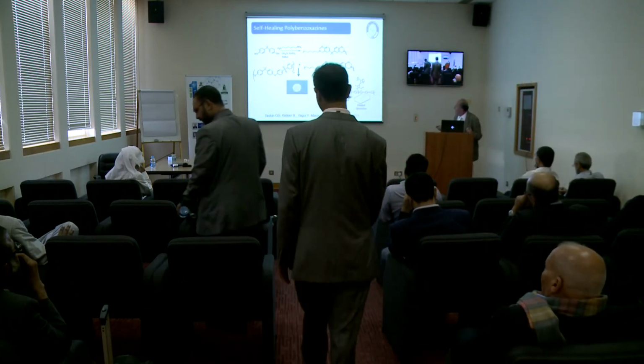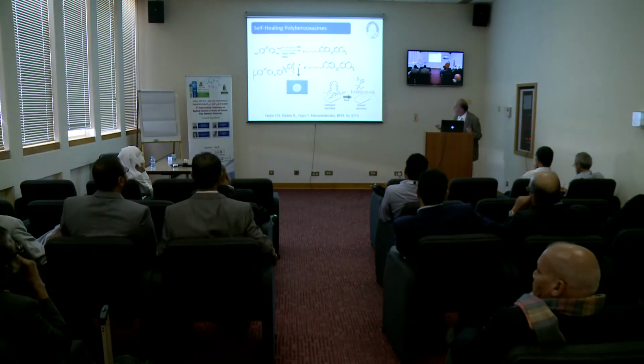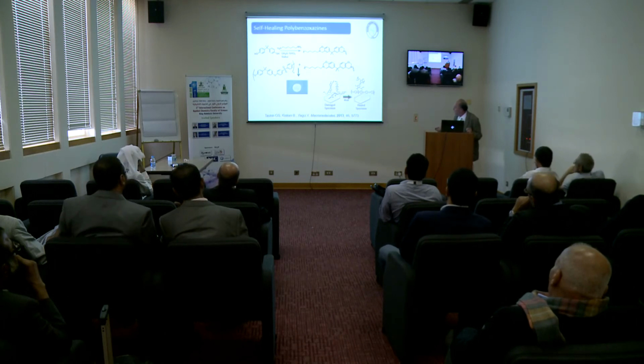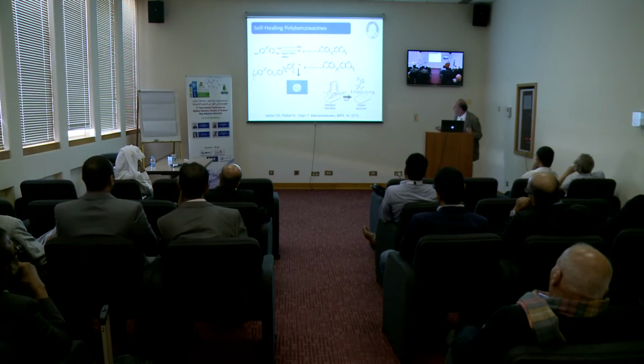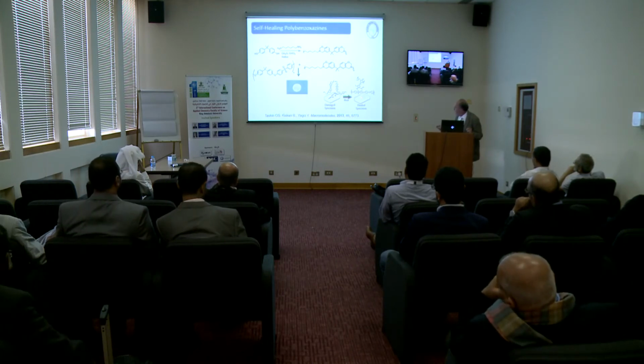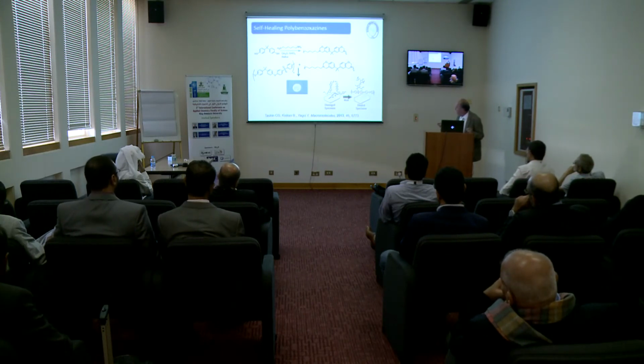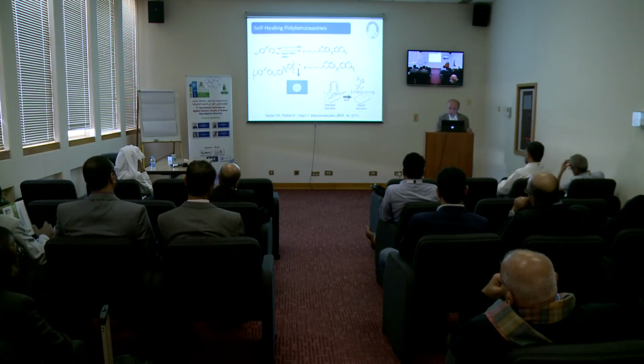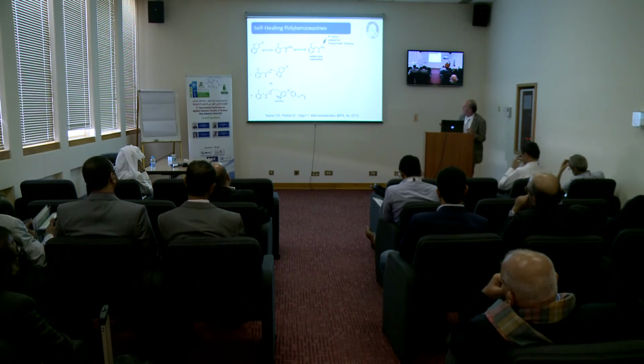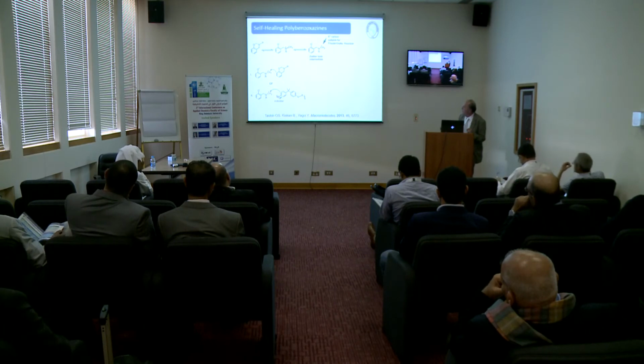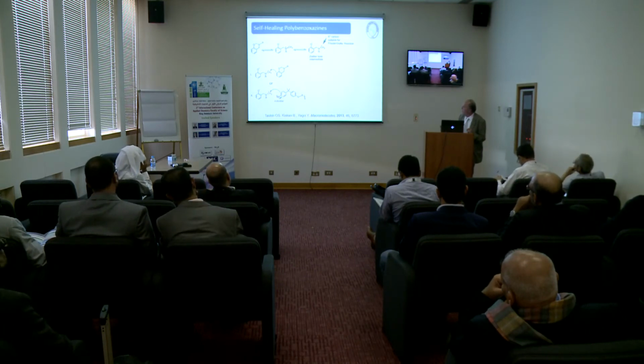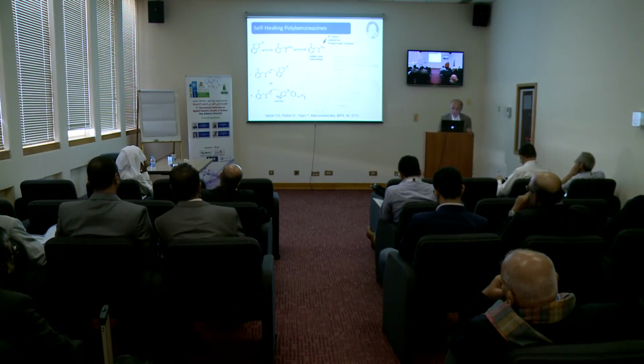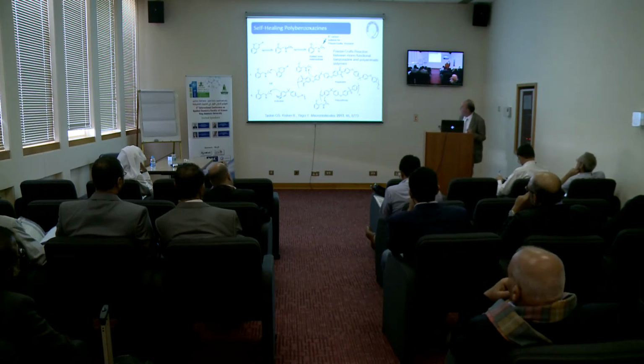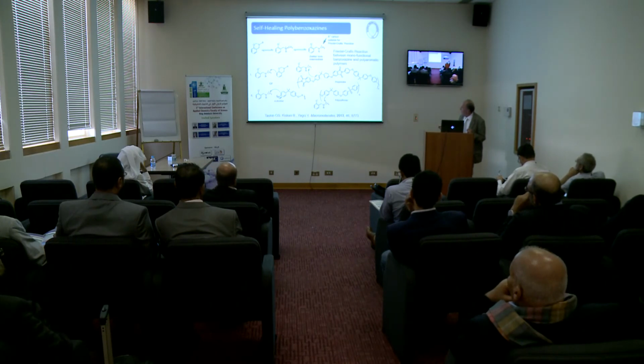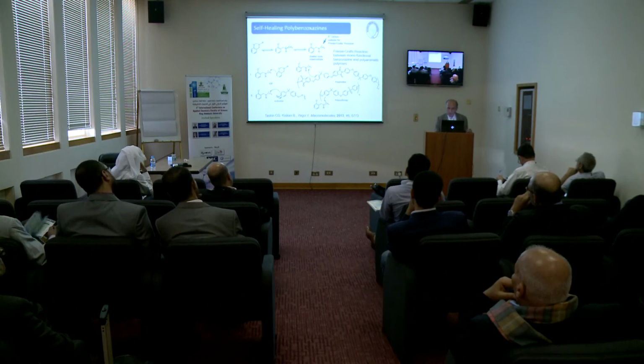So in this case, we have again polysulfone this time, and benzoxazine units as well attached to here. When we make a film and cure them together and damage specimen, by curing you see that there is a ring opening reaction of benzoxazine which can attack the polysulfone and it will cause a self-healing as well. In this case, we represented chemically that the carbocation formed here can attack the aromatic ring or so on, some polar groups. This is the reason to achieve self-healing. As in this case, look, this benzoxazine can attack here or even to polysulfone activated system, and so you have a kind of further cross-linking by thermal means.